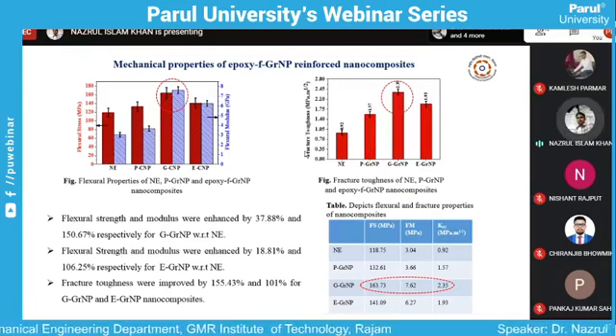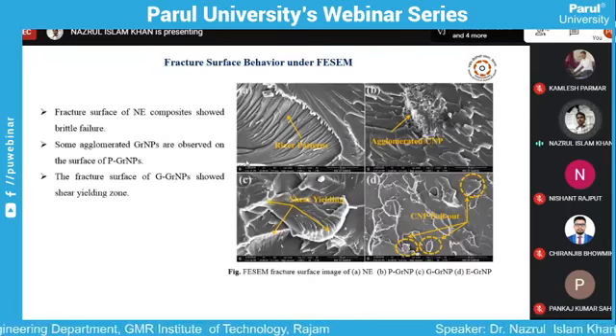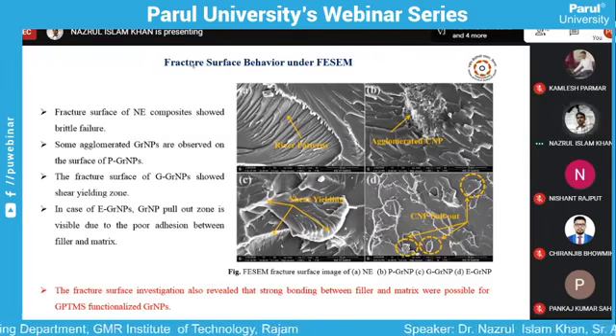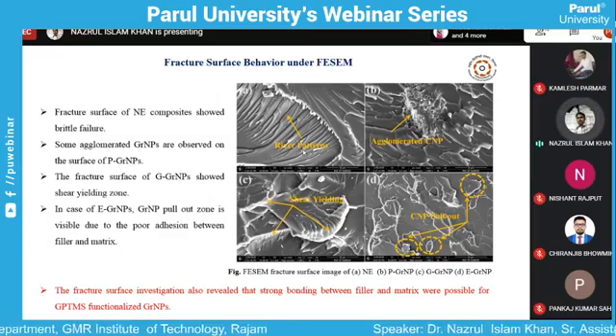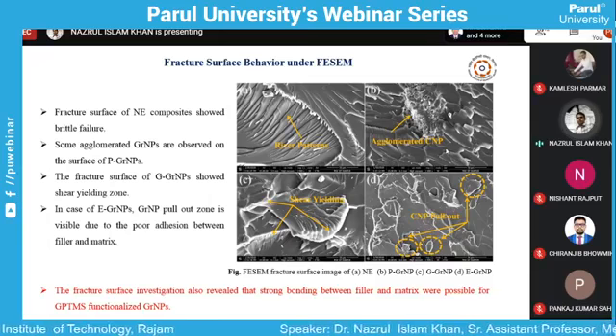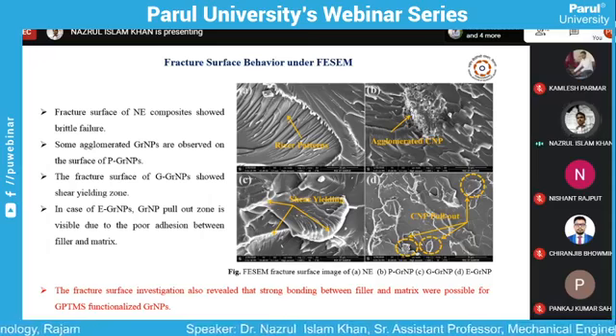Why am I discussing this? I will come back to it later once we start the self-healing part of my discussion. From the surface fracture analysis, we can see that without surface functionalization, if you add this graphene-based nanoparticle, the graphene nanoparticle can be seen as agglomerated.